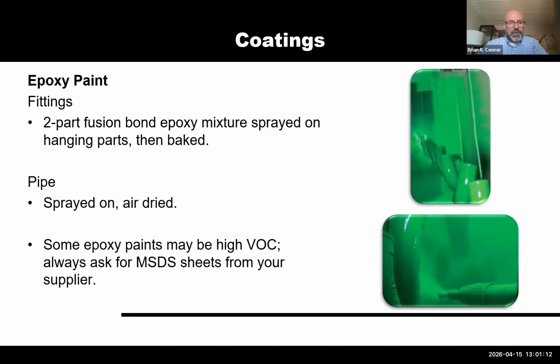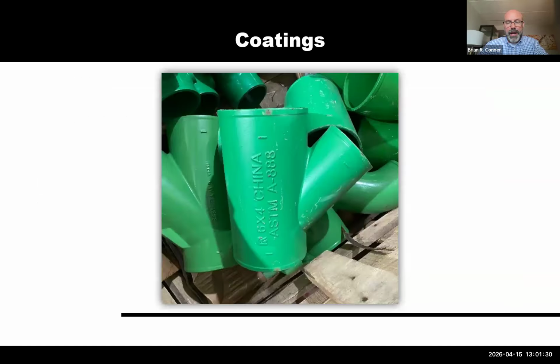So with the offshore, again, it's a two-part fusion bonding epoxy mixture that's sprayed on and then baked on for the fittings. And then with the pipe, it's sprayed on, air dried. You also may want to ask for MSD sheets just to check the VOCs of the supplier of those pipe and fittings. Sometimes those VOCs exceed what is acceptable in North America.